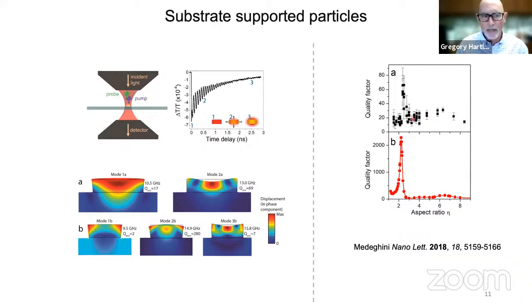The interesting thing about the Vallée and Del Fatti measurements in this paper is that you can see at certain aspect ratios, there's a big increase in the quality factor. What's happened here is that at specific aspect ratios, and this effect is reproduced in these calculations down here.